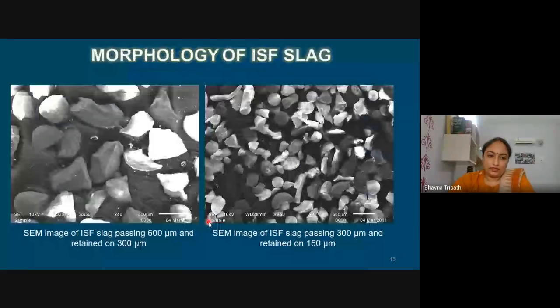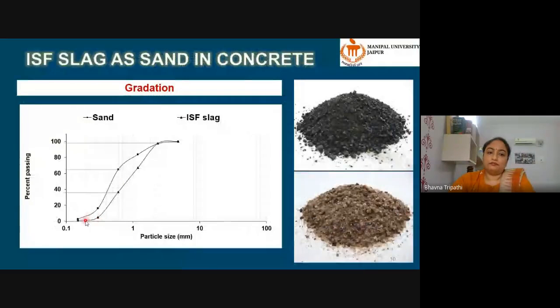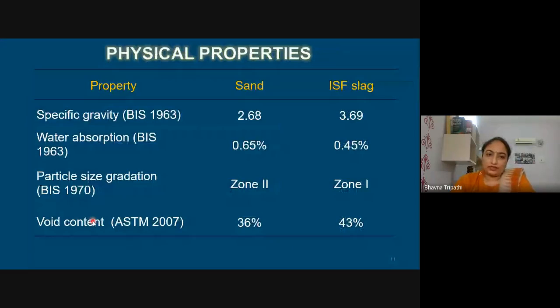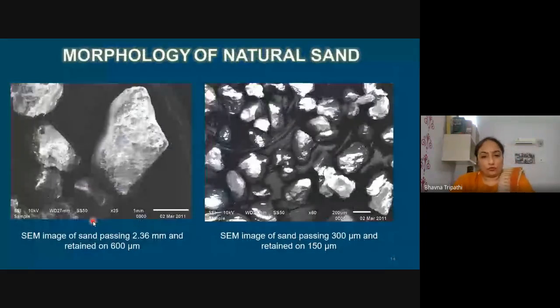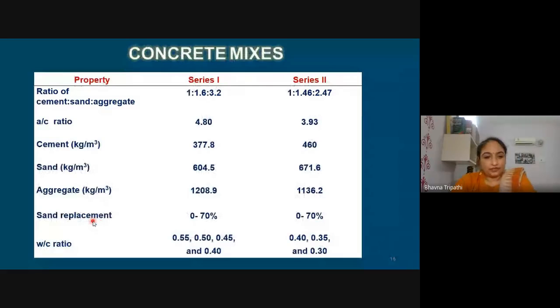You can see here that the 150 micron sieve had at least 5% of finer material. However, here with ISF slag, it is marginal. It is only 1% or so. So if there is a smaller number of fines and you are not compensating it with another material, then it becomes difficult to prepare mixes with a replacement higher than 70%. So we had studied all the concrete mixes up to 70% replacement.